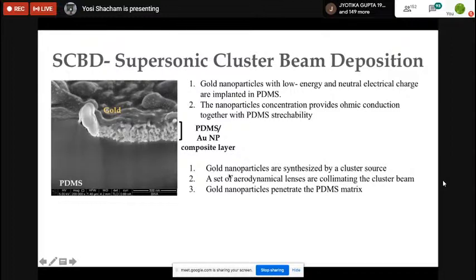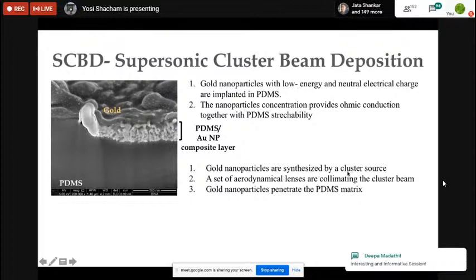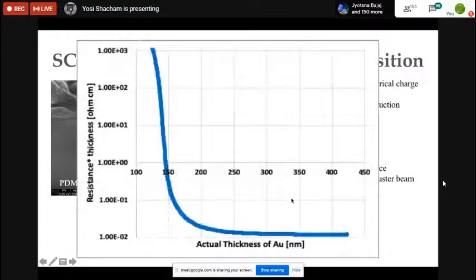And the gold nanoparticles are synthesized by a technology called cluster source. A set of aerodynamical lenses collimate the cluster beam, and the gold nanoparticles penetrate the PDMS matrix. And we can actually, Professor Milani is measuring resistance against the actual thickness of the gold, and you can see that initially the resistance is very, very high.